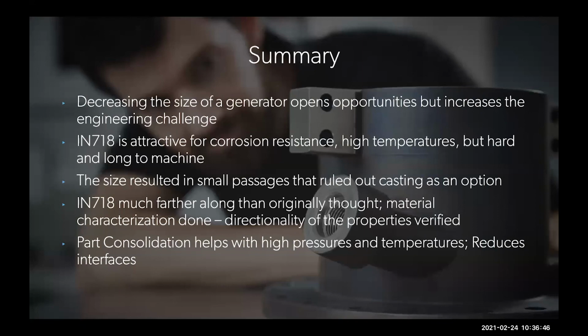And the reason we're going with Inco 718 is because we have a high temperature, high pressure, corrosive environment. Supercritical CO2, if you get a little bit of water mixed in, which is possible, you can have what they call carbonic acid, which is a corrosive environment. So the other part that's challenging with Inco 718, it's a very tough material, but it's very, very tough to machine. And that's why it takes so long and was so expensive to make a part out of it.